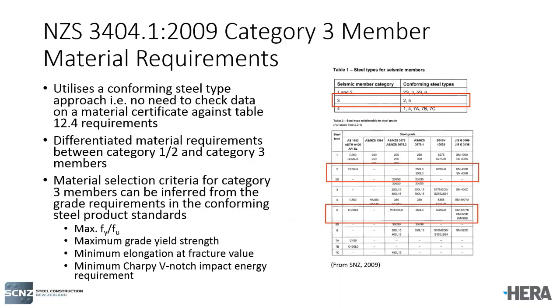Having said that a conforming steel type approach was used for category 3 members, it doesn't mean that we can't infer what material selection criteria lay behind those conforming steel types. If you go to the product standards, for a Type 2 and a Type 5 steel, you can determine an FY over FU ratio maximum value for those steel types. You can calculate what the maximum grade yield strength was for the Type 2, Type 5 steels. You can identify what the minimum elongation at fracture value was, and what the minimum Charpy V-notch impact energy requirement was.